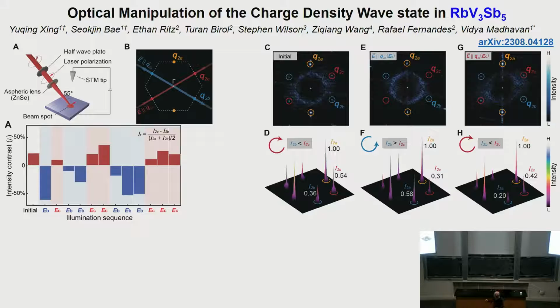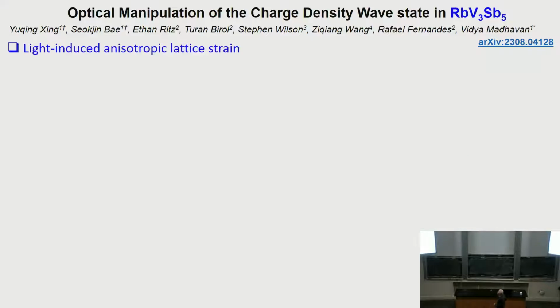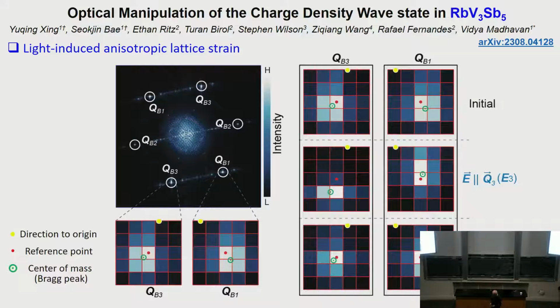Can you actually see the Bragg peak location? She says she can. So these are very high resolution STM measurements, and she can really see the light-induced anisotropic lattice strain. So these are now just the Bragg peaks. This is not even the CDW peak. You look at the 6 Bragg peaks, and you blow it up. This is where the red dot is supposed to be if everything is isotropic and perfect. But no. For this peak intensity, these are the 4 pixels. You look at the center of gravity, it is here. For this peak it is here. So this Bragg peak never sits where it's supposed to be.